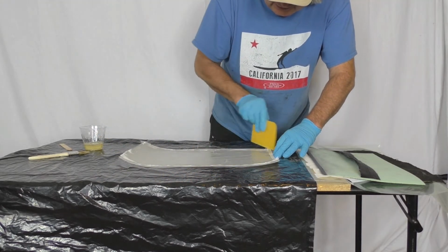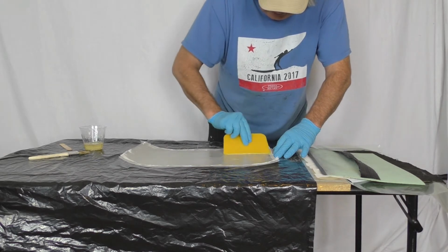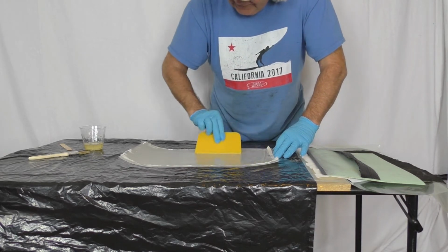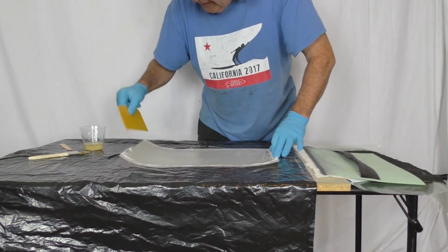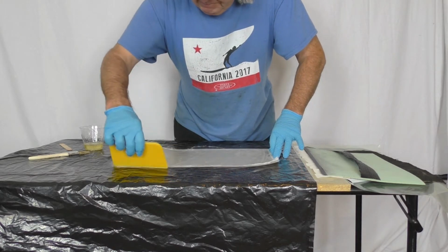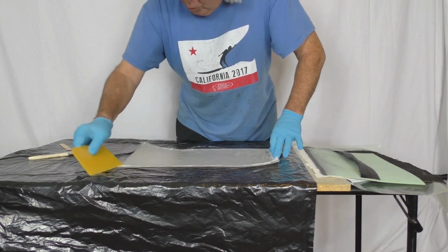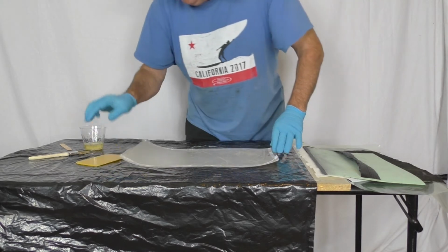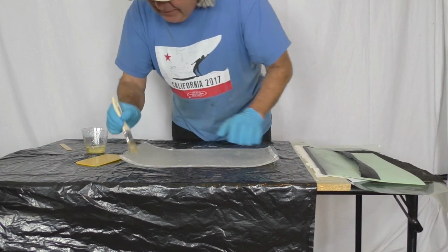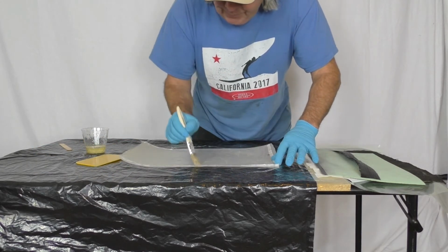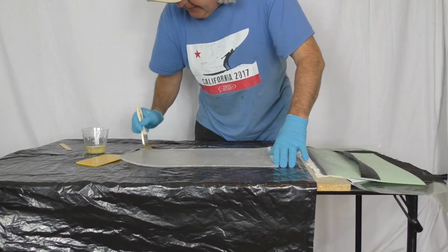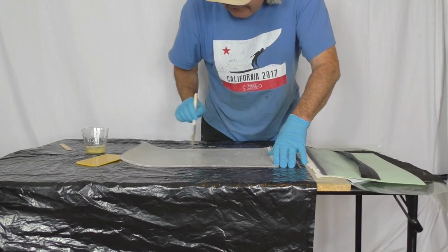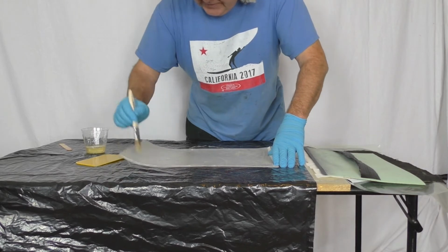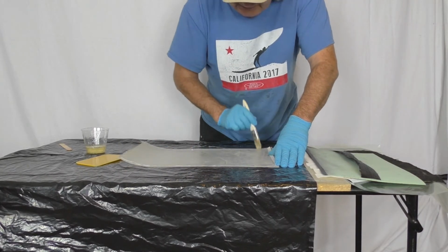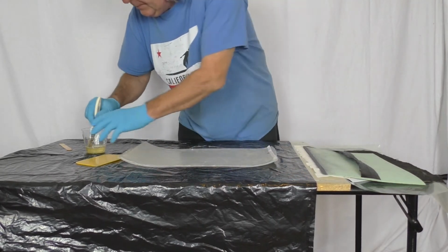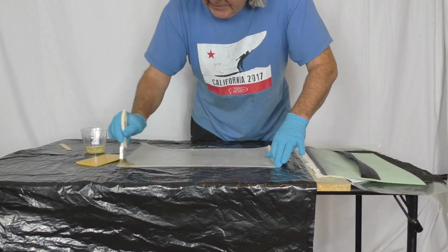We want to make sure that this cloth is fairly wet. We don't want to squeegee it dry because we need a little bit of excess epoxy to bond the foam core in place. If there's not enough extra epoxy, you get a very poor bond to the core material, and that's a bad plan. Now, some ultralight aircraft are built such that the designer says, hey, you got to spread